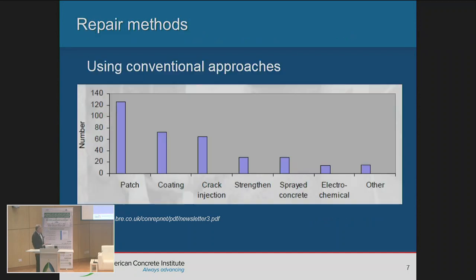So here are the structures. Those structures were repaired using the state of the art at the time of the repair, using conventional methods. Again, a repair could be done under more than one method. Could be patching, could be crack injection, so it was documented under more than one of those categories. After that was done, they observed and checked how long that repair lasted. What they found out is that within 5 years, about 20% of the repair work failed. Within 10 years, about 70% of the repair work failed. That's really substantial. Imagine yourself being an owner, you hired somebody to do your repair work, and within a few years it failed. You as an owner will not be happy, right?